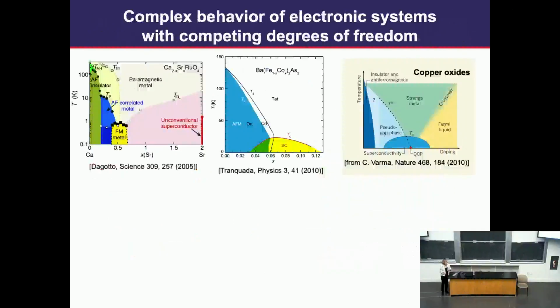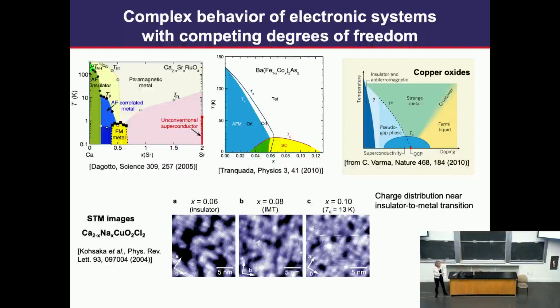And as I said, the quantum materials have many competing degrees of freedom. They have complicated phase diagrams, which is why there are so many people studying them. And because of this competition, as I said earlier, one may expect also some glassiness, which indeed has been seen in various experiments. Here, just as an illustration, is a very old, not very good resolution STM image of one cuprate, where on the insulating side you can see these bright areas are charge distribution. You can see it's inhomogeneous on the nanoscale.